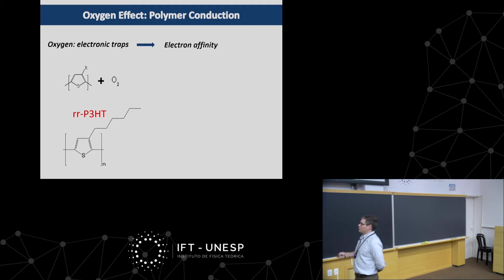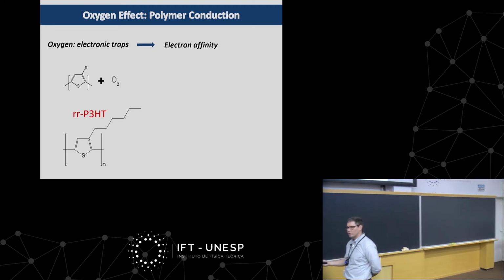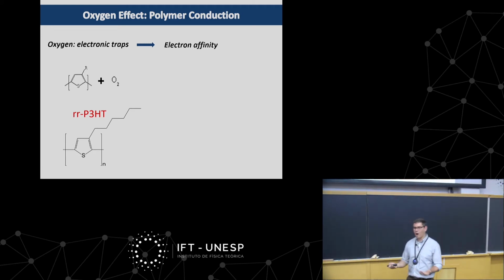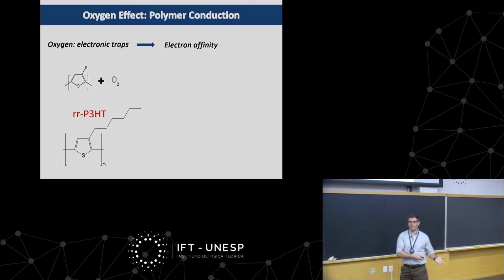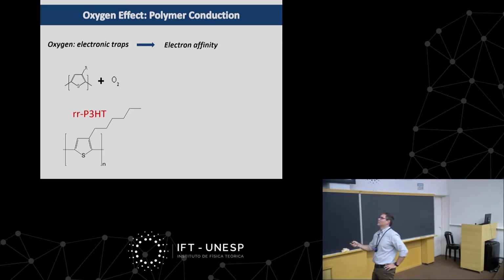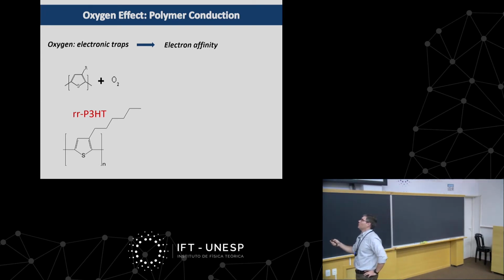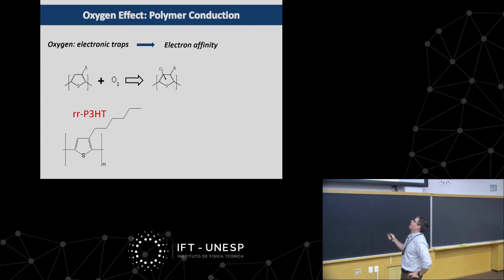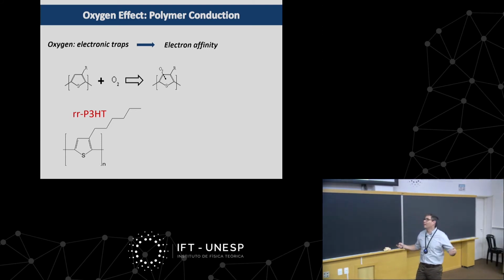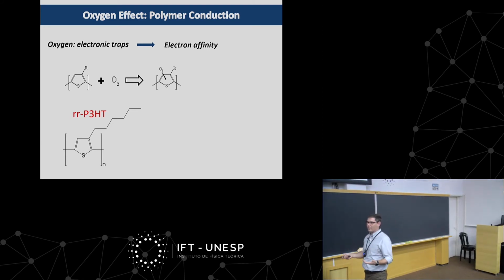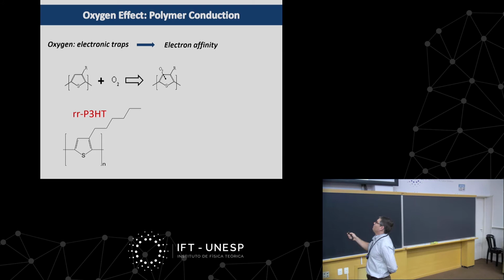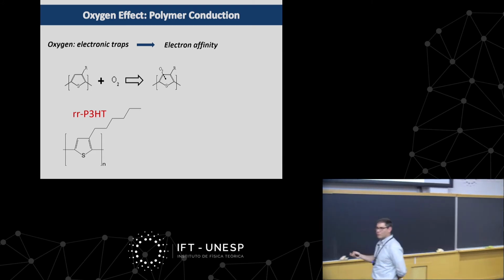And we did some sort of oxygen exposure to see how that oxygen would actually degrade the material. And the way it works, so you have here the backbone, or the conjugated chain, plus an oxygen. And because of the electron affinity, which is very high, like fluorine, oxygen is very electronegative. The oxygen actually sits very close to the conjugated backbone.